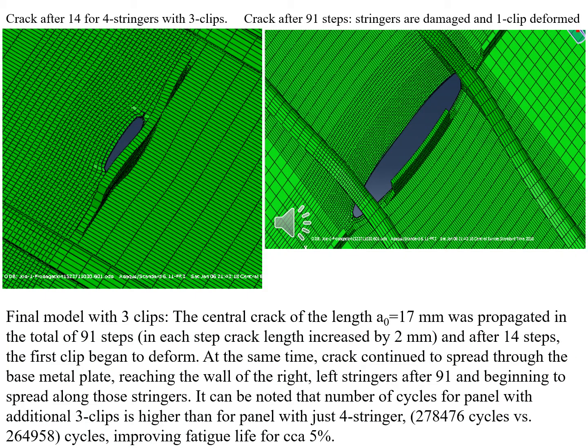Finally, we have simulated also the most complicated case, and that is with additional 3 clips, which were welded also in an attempt to provide additional number of cycles and to prolong the life. So here we have such a model. Slightly different initial crack length was used, and to be honest, we did not get quite an improvement by adding clips. As you can see, there was a slight increase in number of cycles, 278,000 versus 264,000. So just 5% of improving in fatigue life.